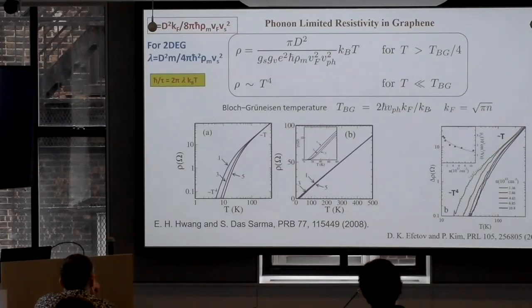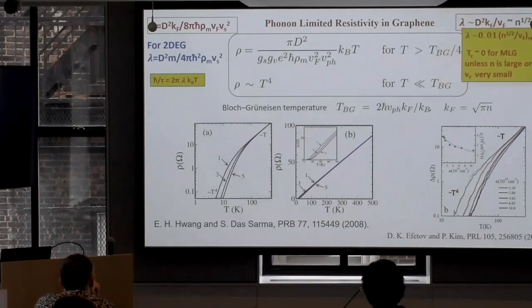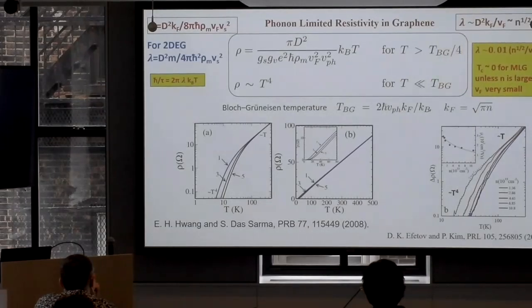And so we get an estimate of the deformation potential coupling, which I think is of the order of 30 electron volts. And when you put in the 30 electron volts, you get a lambda which is very, very small. This lambda is a dimensionless effective electron-phonon coupling that comes into the theory of superconductivity, made famous by the great late McMillan. And this is essentially zero. It's 100 microkelvin or 50 microkelvin, something like that. Now, can you get superconductivity?